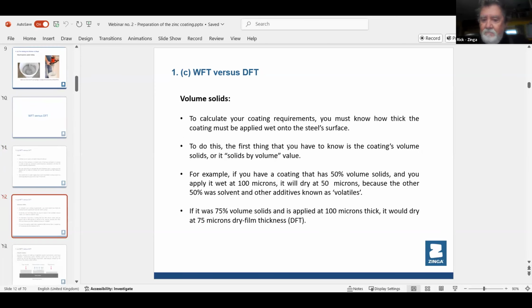So the volume solids, okay. If you look at your data sheet, Zinga is 58% volume solid. So if you apply it wet at 100 microns, it's going to dry at 58. Because that's how much solid zinc is inside that. The rest is binder and some solvent. So what we're saying here is, if it's 50% and you apply wet at 100, it'll dry at 50. But because Zinga is 58 and you apply it at 100, it'll dry at 58. That's how simple it is. Okay.